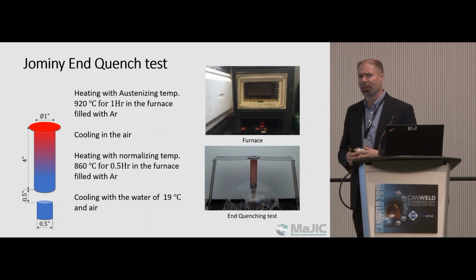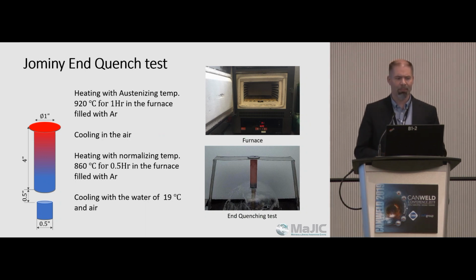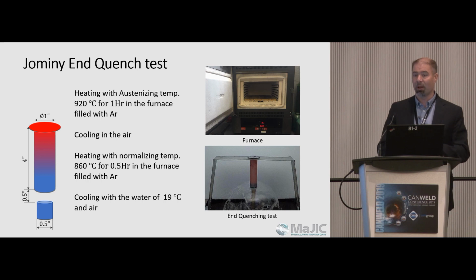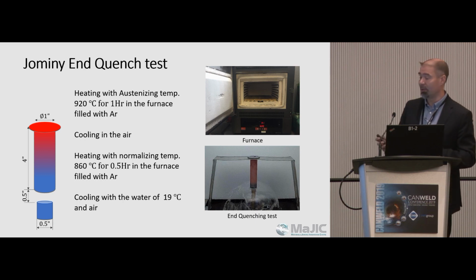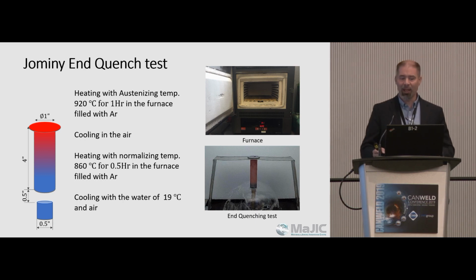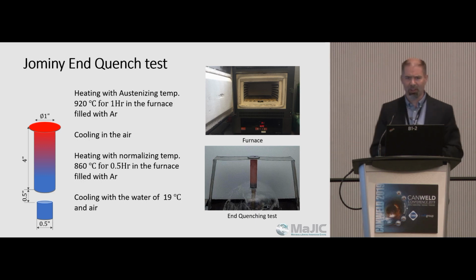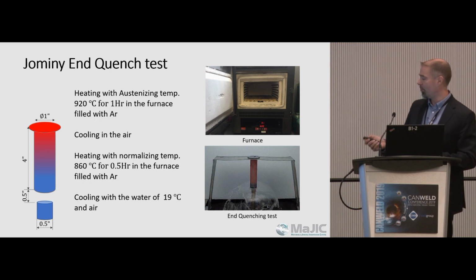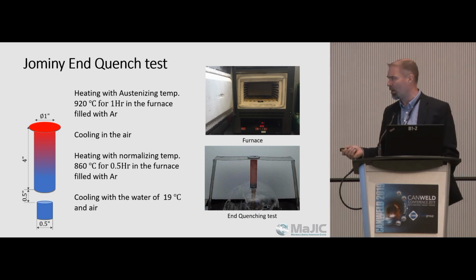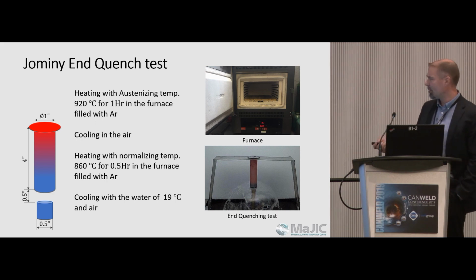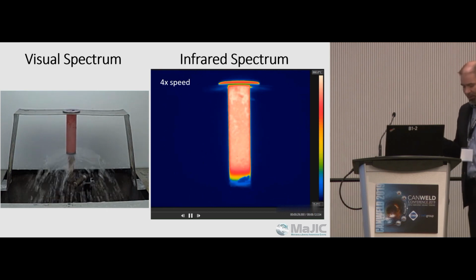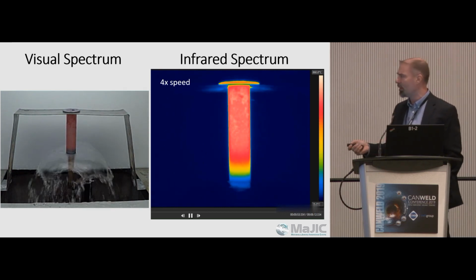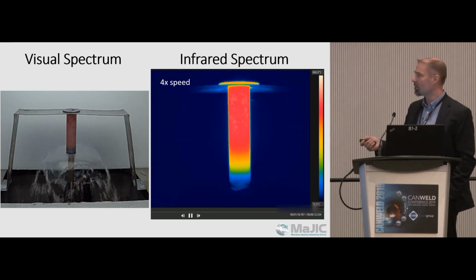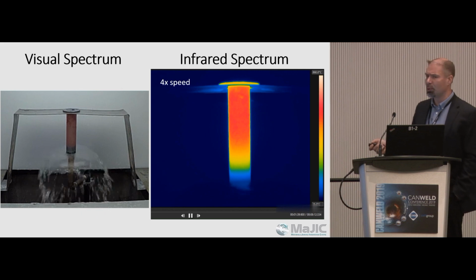A little precursor on the Jominy end quench. The Jominy end quench is a test where you take a 1-inch diameter cylinder, heat it up, let it cool down. Heat it up again, and place it in a specific fixture that forces a constant flow of water against one end. And what that does, see if these videos work. What that does is it provides a very rapid cooling at one end of the sample and a very slow cooling, or a gradient of cooling rates throughout.